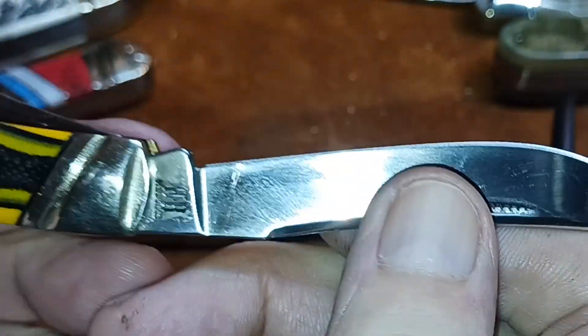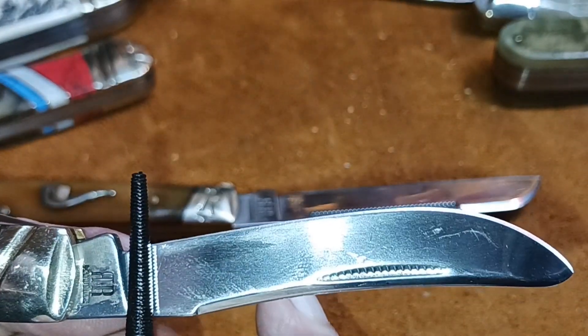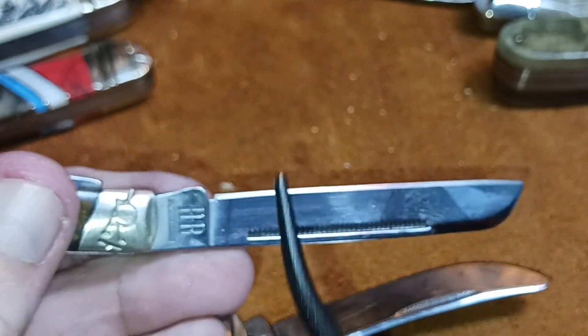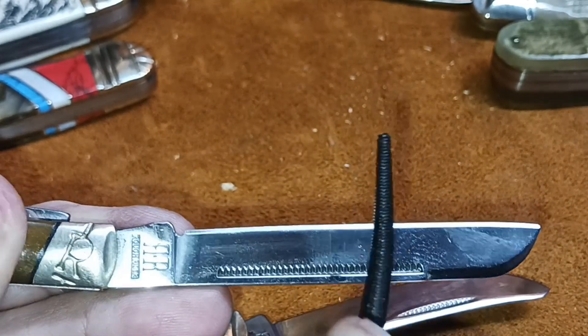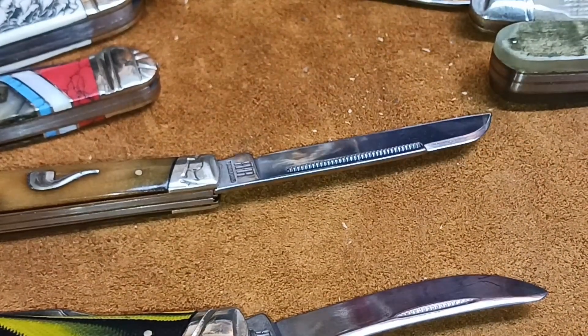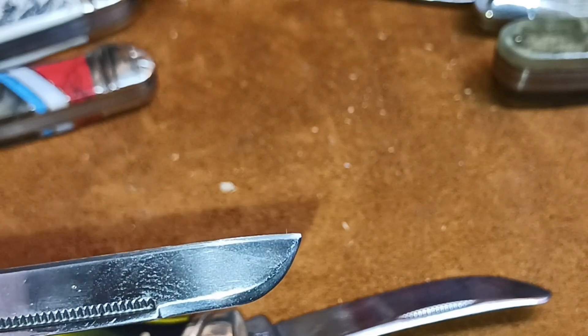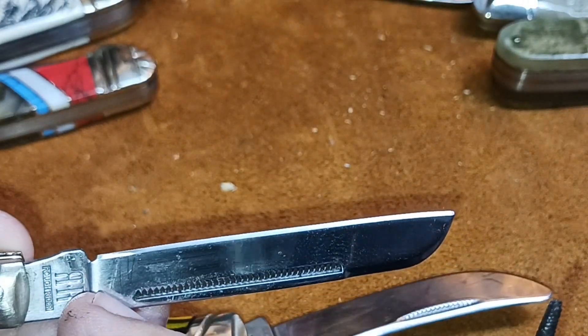Going back to 60, putting it on the 440A. It slides. There's a spot where it had dug in before. Now trying the VG-10 at 60 — oh yeah, just took a chunk out, see how shiny that is? Let me try 55 on the 440A — just scraping right there at 55 and it's not shiny. That one at 60 was shiny.